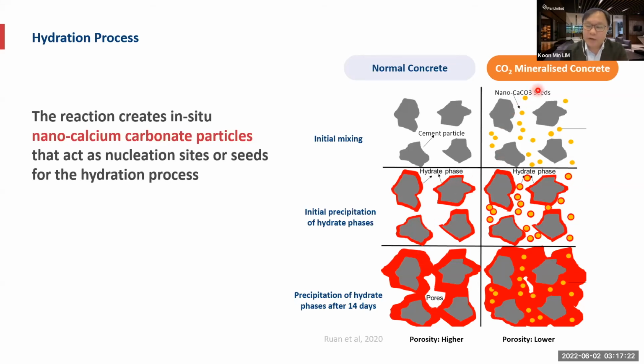Now, let's take a look at the CO2 mineralized concrete. Apart from the cement particles in the concrete, the yellow dots are the nano calcium carbonate seedings that are formed around the cement particles. And during the initial precipitation hydration phase, you can see that the hydration products in red not only form on the cement particles, but are also formed around the seeding sites. And after 14 days, you can see more hydration products formed around the cement particles as well as the nano calcium carbonate seeding sites, as compared to those of the normal concrete.